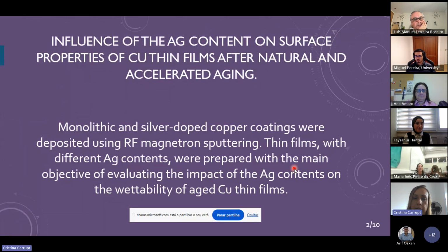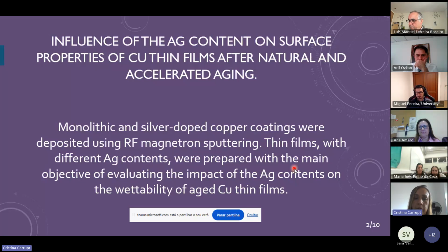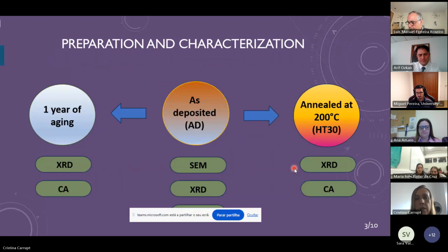So to understand the effect of aging on these films, we developed monolithic and silver-doped copper coatings deposited using magnetron sputtering, PVD. Films with different contents of silver were prepared with the main objective of evaluating the impact of aging and silver content on the wettability of silver-copper films. So the samples were divided into 3 different groups. The first one was kept as deposited. A part of the samples was annealed at 200 degrees, and the last one was left exposed to normal temperature and humidity conditions for 1 year. And all of the samples were characterized.